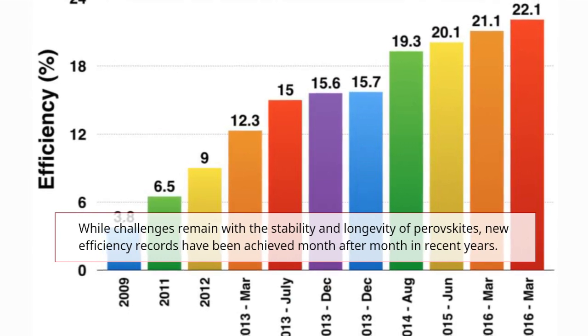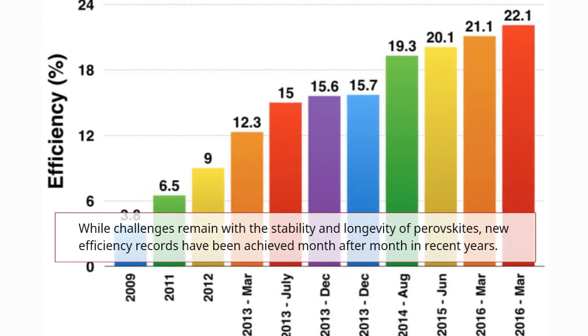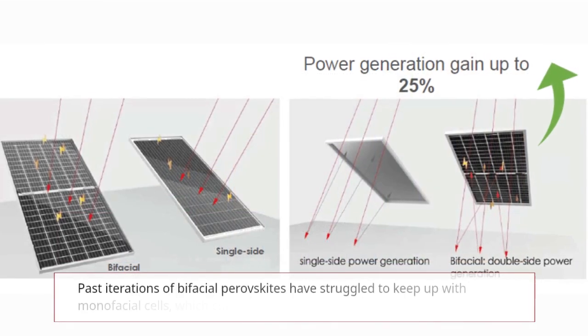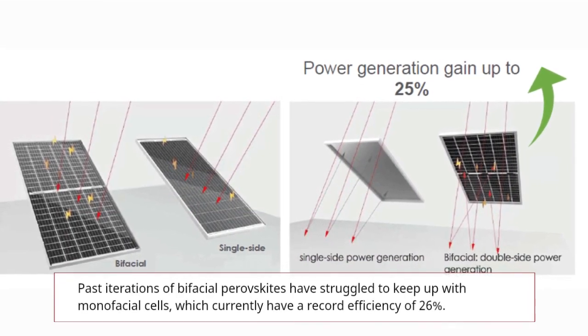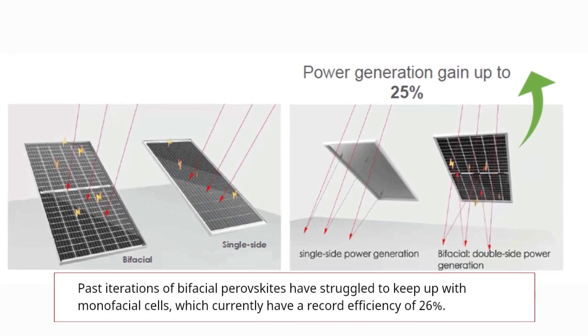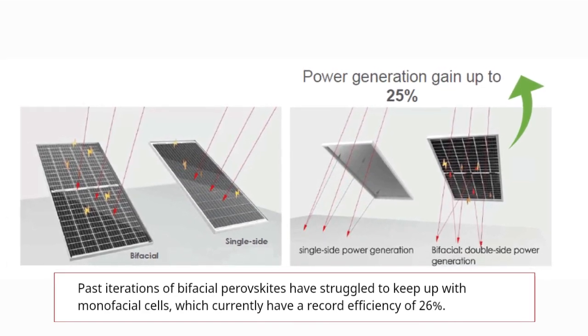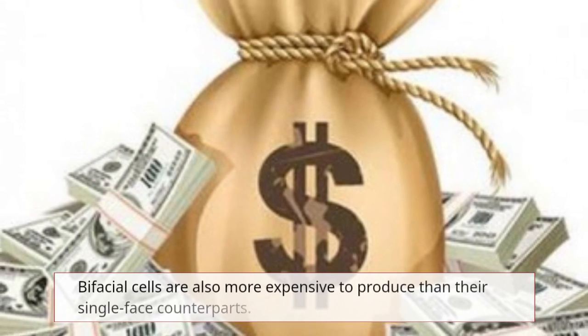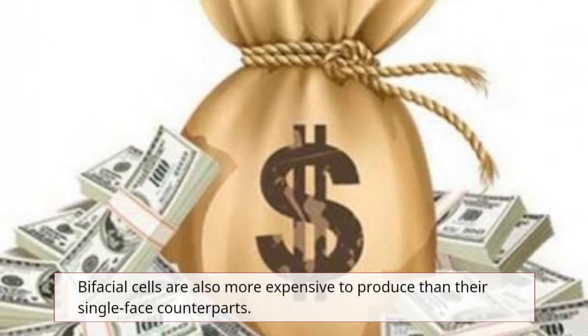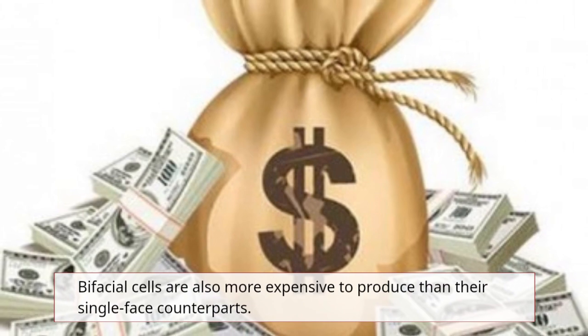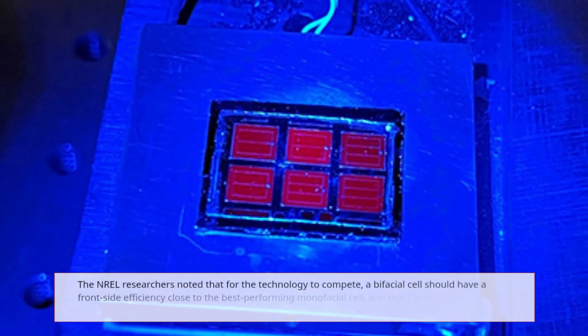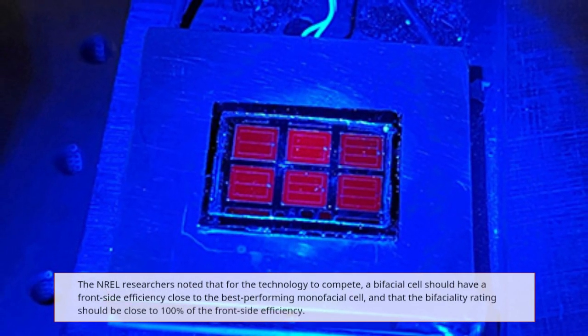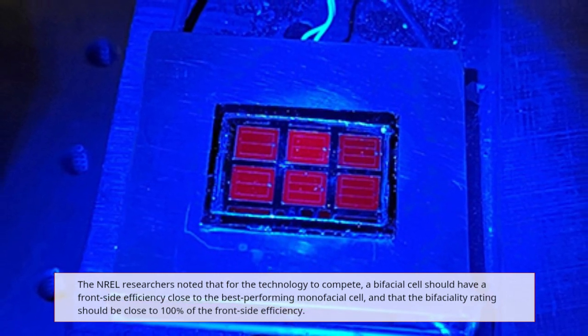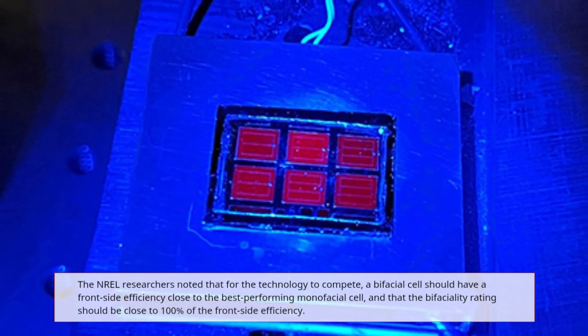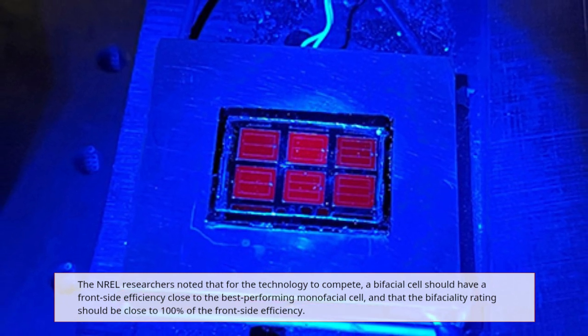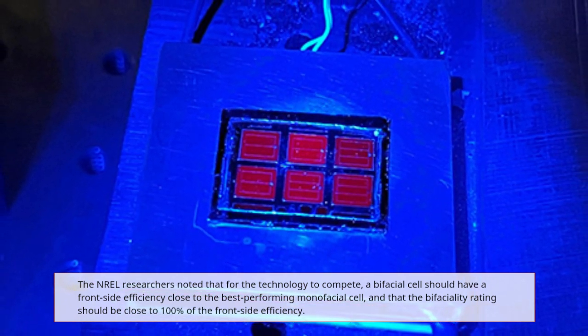New efficiency records have been achieved month after month in recent years. Past iterations of bifacial perovskites have struggled to keep up with monofacial cells, which currently hold a record efficiency of 26%. However, it is also noted that bifacial cells are more expensive to produce than their single-face counterparts. So the NREL researchers noted that to compete, a bifacial cell should have a front-side efficiency close to the best performing monofacial cell, and that the bifaciality rating should be close to 100% of the front-side efficiency.